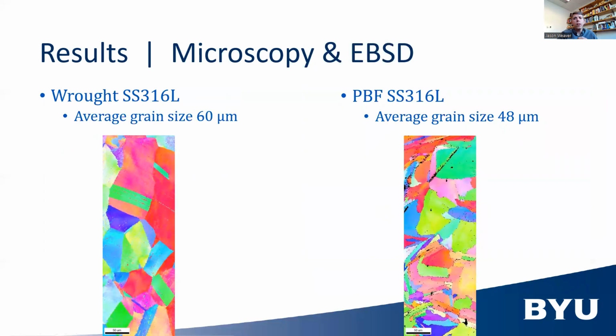And then finally, here are the grain maps. On the left, we have our wrought stainless steel, and on the right, our powder bed fusion stainless steel. You can see that the grain size of the powder bed fusion is a little bit smaller, a little finer. So instead of 60 microns, we're down to 48 microns.